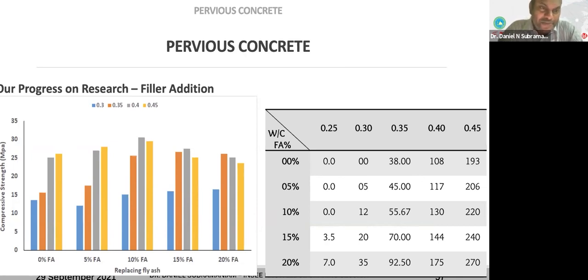And this shows you the strength that we can get with different water cement ratios. For the conventional one also, most of the time we have used about 10% substitution. Now, one thing I would like to note is that for all the other studies in the previous ones, we used hydraulic cement. Conventional cement and hydraulic cement don't have a lot of impact on strength when it comes to pervious concrete, because we are talking about the lower range of strength, so it doesn't have any impact at all. But for this study, we used OPC because we are substituting with fly ash. Probably in the future we should be able to do it with hydraulic cement as well.